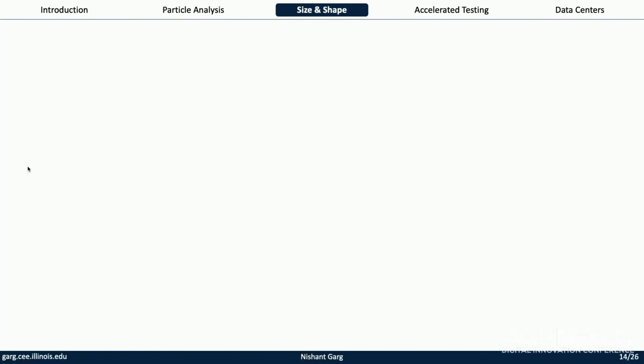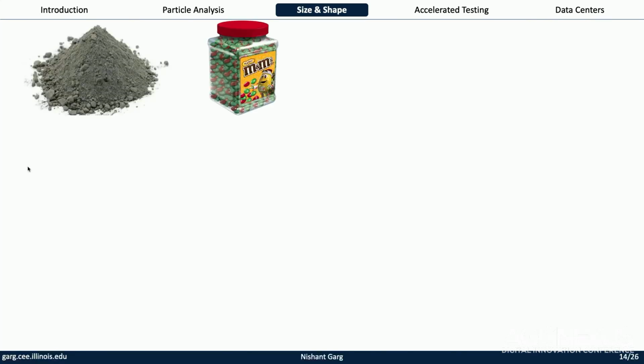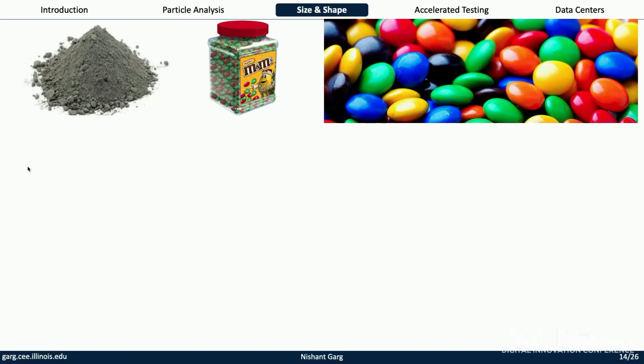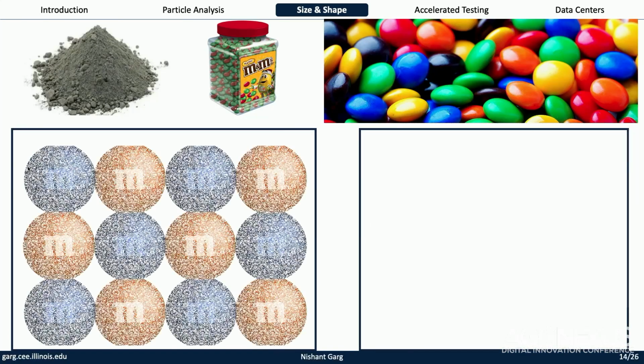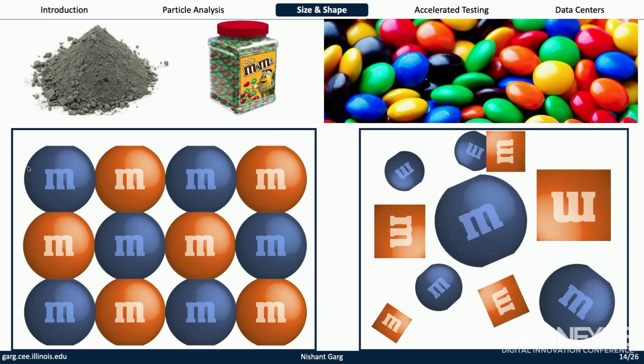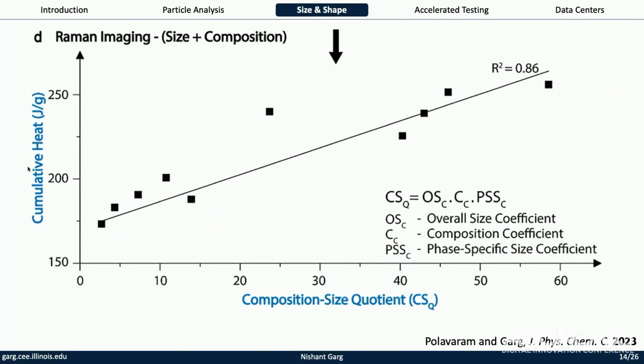But really, again, what's the value of this, right? The value here is that if you think about all of the cement powder individual particles like M&Ms, you can think that they're all equal size, equal shape, but in reality, they're all different sizes and shapes and randomly oriented. And we came up with this very simple empirical coefficient called the composition size quotient, where we combine the composition of the cement and the size into a single parameter. And this parameter can then predict the 3-day cumulative heat of that cement, which is a good predictor of the overall hydration and the performance of that cement, right? Again, just looking at the size and shape and the composition initially.